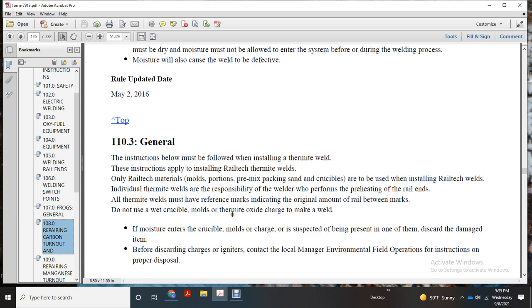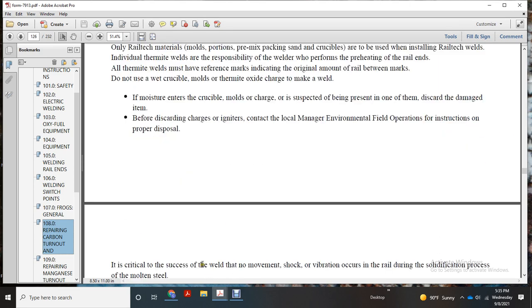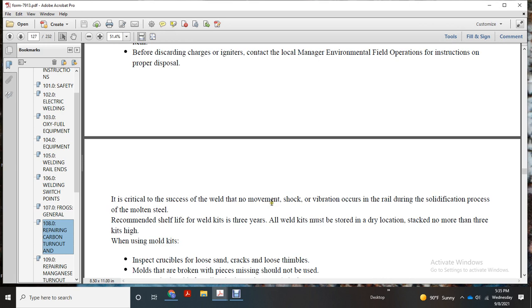Do not use the wet crucible mold with the thermite oxide charge to make a weld, as moisture will enter the crucible mold. Recharge if moisture is suspected to be present in one of them; discard the damaged item before discarding charges or igniters, contact the local manager environmental field operations for instructions on proper disposal. It is critical to the success of the weld that there is no shock or vibration of the rail during the solidification process of the molten steel. The recommended shelf life of the weld kits is 3 years.